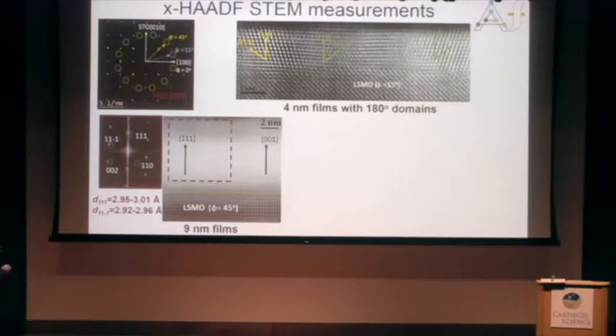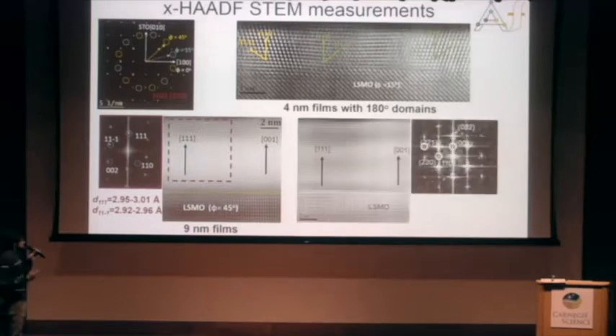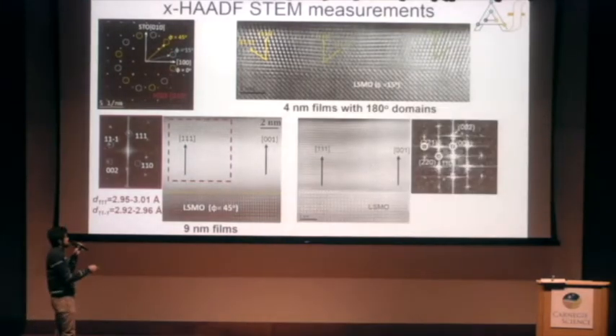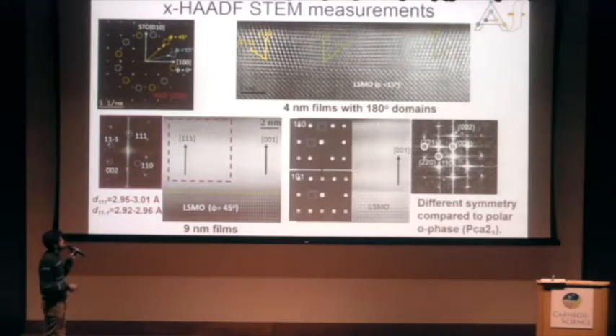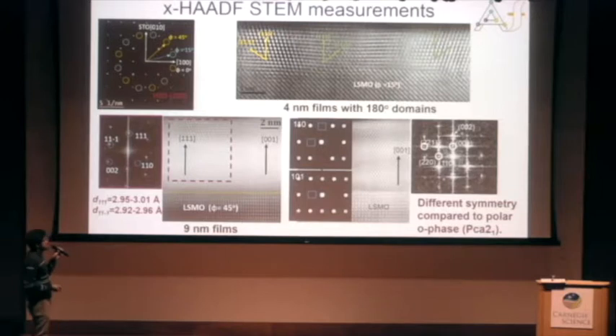So if we calculate what the d-spacings are, the d-spacing of 111 is different from 11-1, and this is indicative of the fact that we don't have the conventionally reported polar orthorhombic phase. In an orthorhombic phase, these are supposed to be the same. Same thing if you analyze the 001 domain, you do find some spots which are forbidden in a Pca2_1 orthorhombic phase. What phase is this?